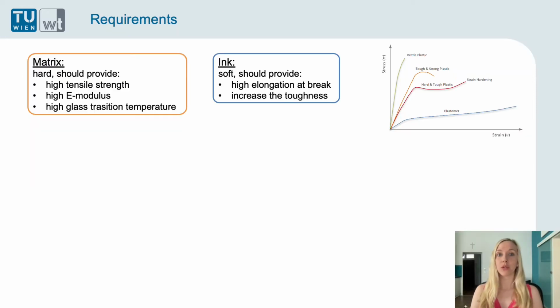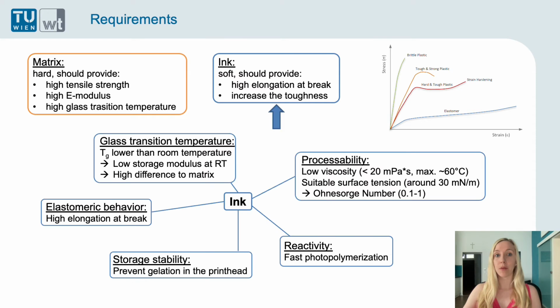So we have a matrix material which should be hard and should provide a high tensile strength, a high E modulus and a high glass transition temperature. And we have a soft ink which should have a high elongation at break and increase the toughness of the matrix material due to this shielding effect. And I'm working on the development of this soft ink.